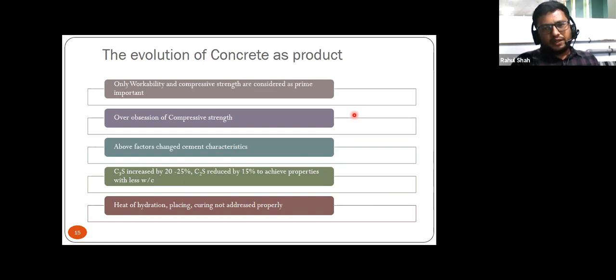So slowly and gradually over the period of time, let us say last 20 years, 30 years, 40 years, these factors have changed the characteristics of the cement. Like if you compare the chemical analysis of the cement, the C3S content was increased by 20 to 25 percent, C2S was reduced by 15 percent to achieve the properties. Which properties? To achieve greater compressive strength with lesser water cement ratio, right? So if we work with lesser water cement ratio along with some admixtures, we may get good workability, and by lowering the water cement ratio we can get the higher strength, right? So our obsession is taken care of, but this particular practice has led to some problem.